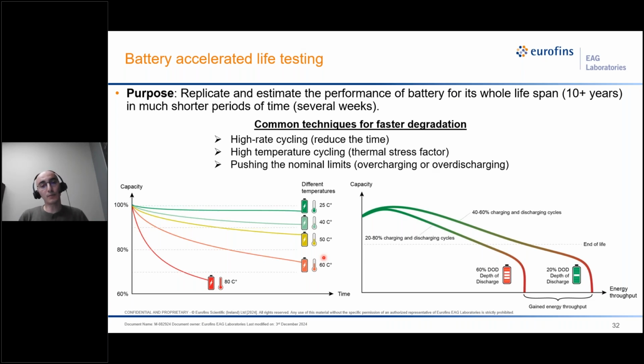As you can see in the first graph, as you increase the temperature, the expected lifetime of the battery, the expected number of cycles that it can undergo, is getting shorter. Or we can push the nominal limits. We can overcharge or over discharge, or change the depth of discharge as it is implemented in this graph. Then it will also allow us to shorten the lifetime of the battery deliberately. And then with these results, we can estimate the performance of the battery in the nominal use.